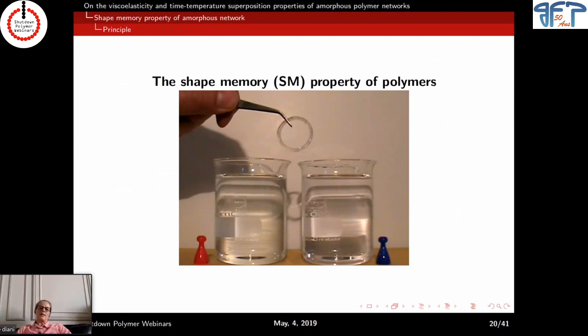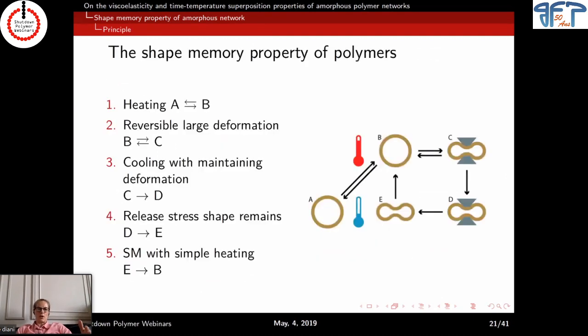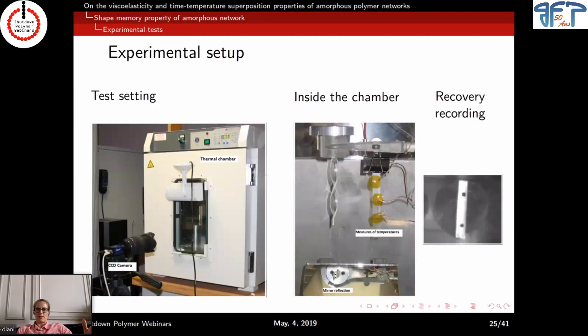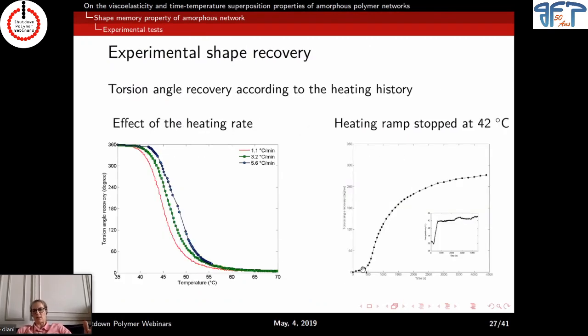Yeah, that's what we did. For example, when we applied here, we started from a temperature that was probably room temperature, 25. We raised until 42 degrees. Here the temperature was going from 35 to 70. Here we stop at 42, and we look at over time how the temperature evolves. So it stopped approximately here, and then we look at the recovery over time.